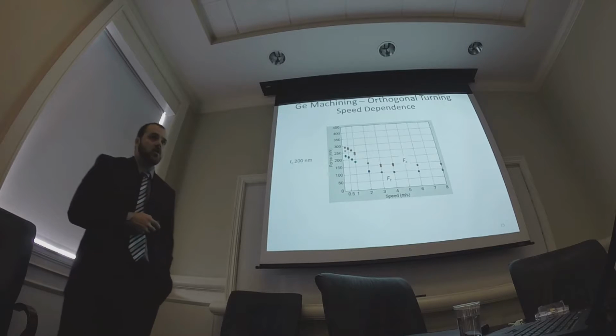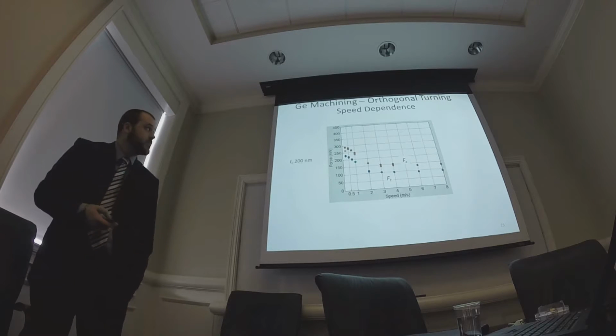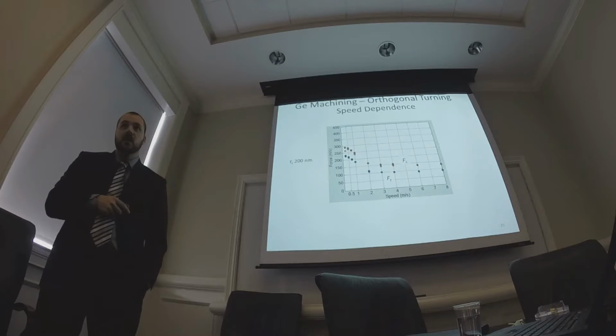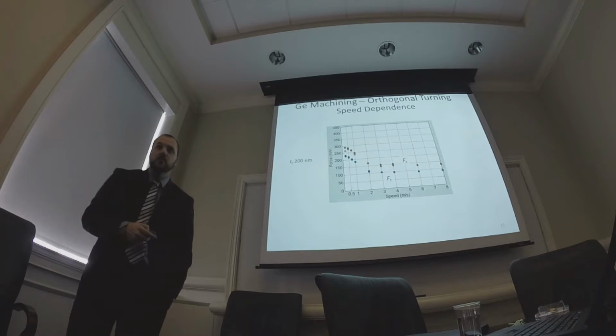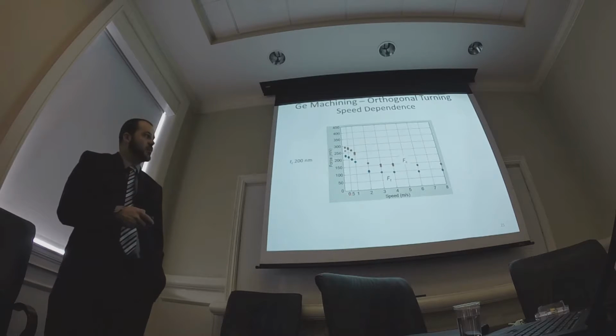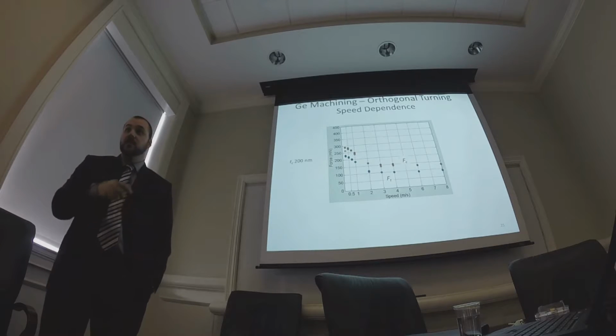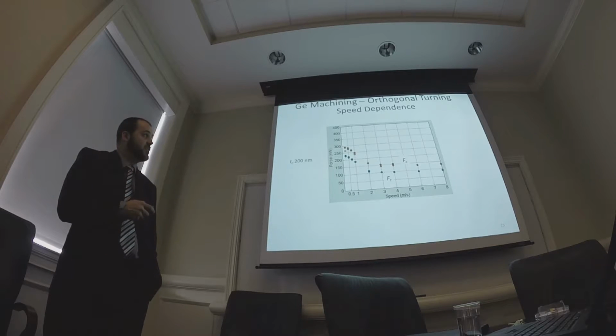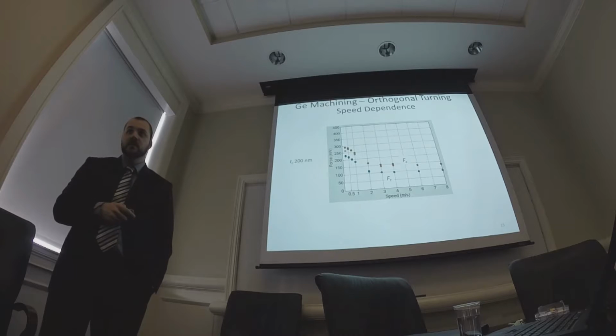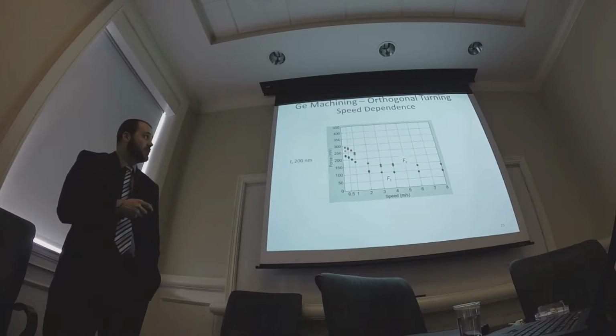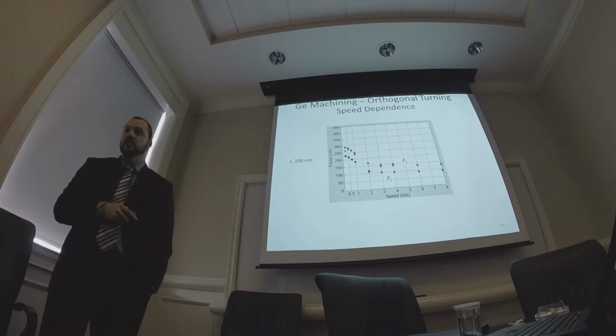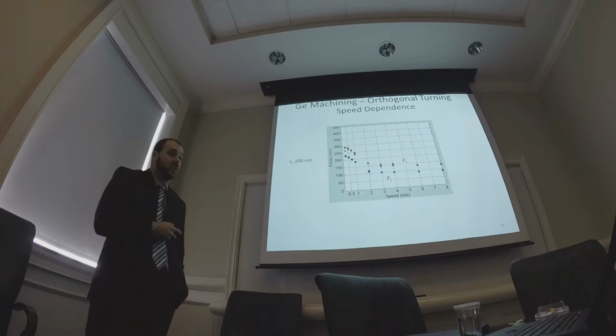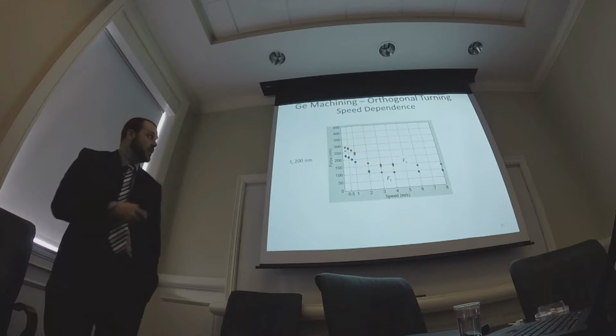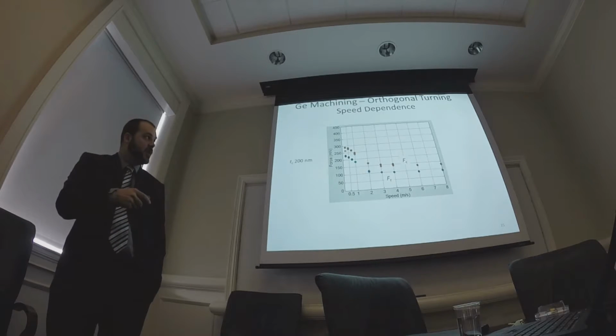So now we move to, is there a speed dependence in germanium? I picked a constant chip thickness of 200 nanometers, again 200 micron chip width, and swept through a similar range of speeds as we did in the RG26, and found a 50% drop in force from 0.25 meters per second to the 4 to 8 meters per second range. A fairly big drop, whereas in the RG26 we saw relatively level force, just small bumps but no trend.